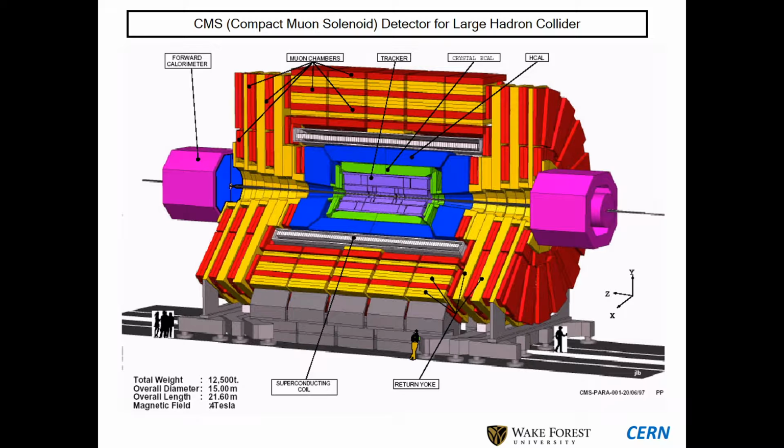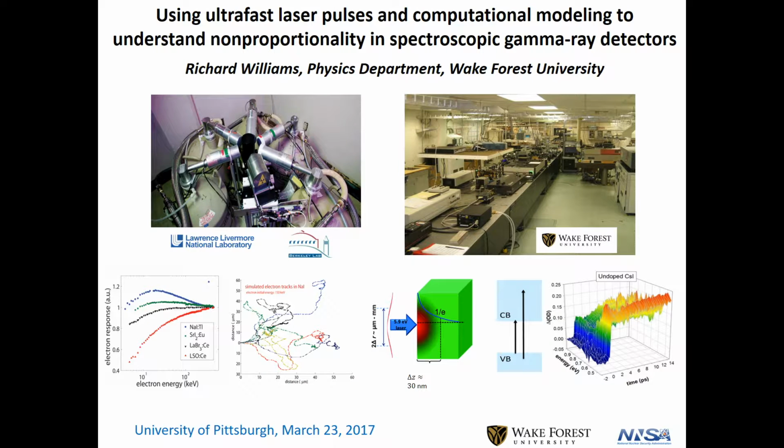And again, scintillators, spectroscopic scintillators, just to define, light up when they stop. Of course, through electromagnetic interactions, you stop a gamma ray fully within the crystal, and it makes a lot of electron hole pairs, and they wind up giving light. And you count the photons of light that come off, and you hope you can interpret that as proportional to the energy of the gamma ray. And of course that gets back to the first slide, this funny word that you probably never come across, non-proportionality. So you hope it's proportional, and you do a lot better if it's proportional, but it's not.